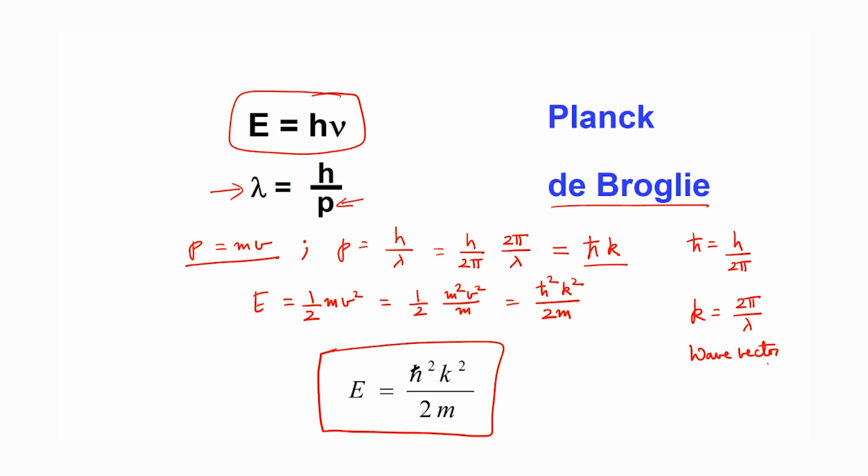Right. So, why is this interesting? This equation is related to the quantum mechanical approach of looking at electrons in solids. Here h bar is a constant, it is h by 2 pi, 2 is a constant of course, and m is the mass of the electron, so that is also a constant. What do we have that is related here? We simply have E, which is the energy, and k, which is the wave vector, 2 pi by lambda, okay. So, when an electron moves with different energies, you have a different wavelength associated with it based on the momentum that it has, and for each wavelength associated with the electron, you can find out the energy associated with it using this equation, right.